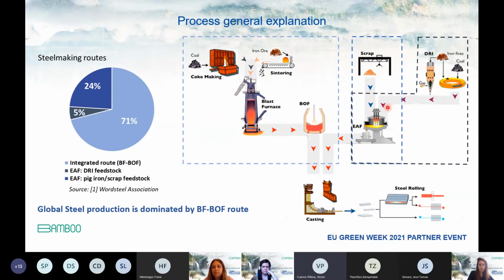Another route is the direct reduced iron. We directly reduce the iron fines using coal and also reducing gas. And this solid product is then melted in an electric arc furnace. On the other hand, if we take scrap from recycled steel, we can also melt the scrap in the electric arc furnace. At the end, we have liquid steel that we need to cast and then give shape, forming typically by steel rolling processes. The first part of the process we call the upstream or primary process, and the second part we call downstream or finishing processes.